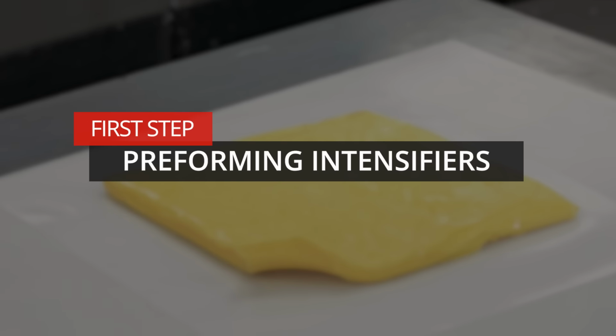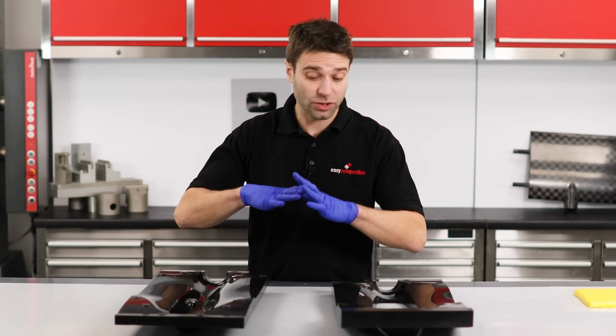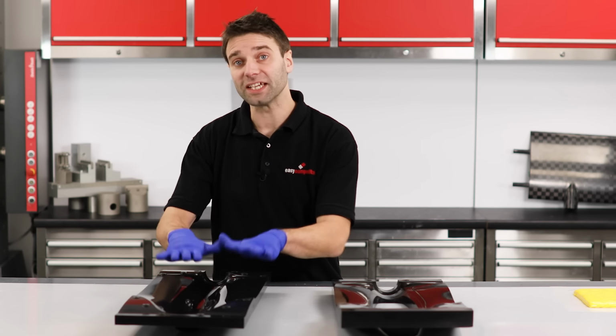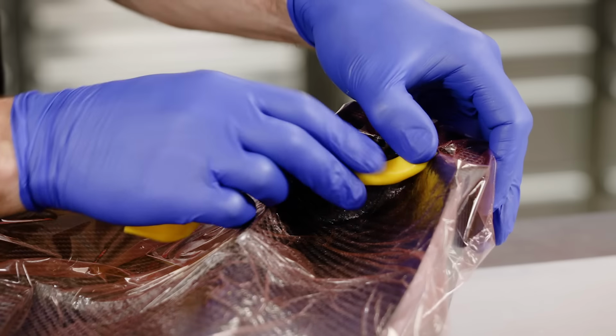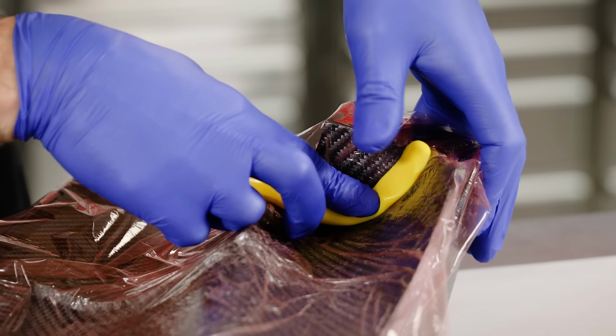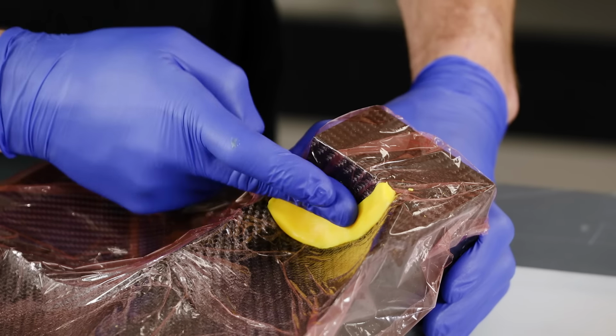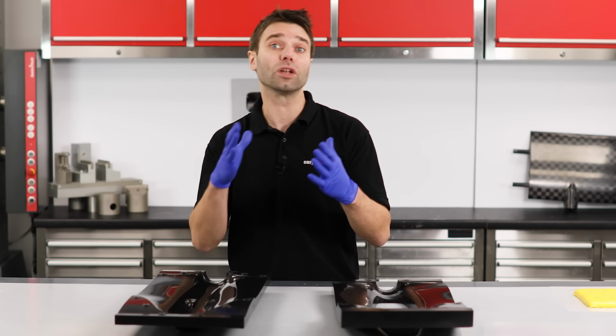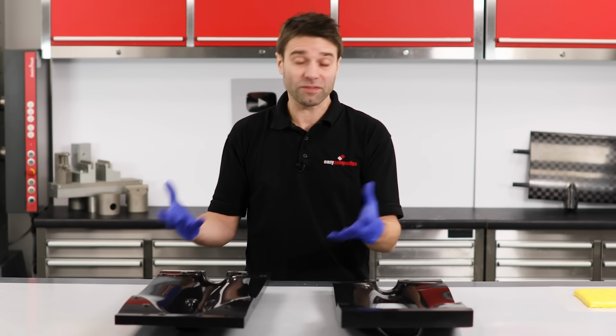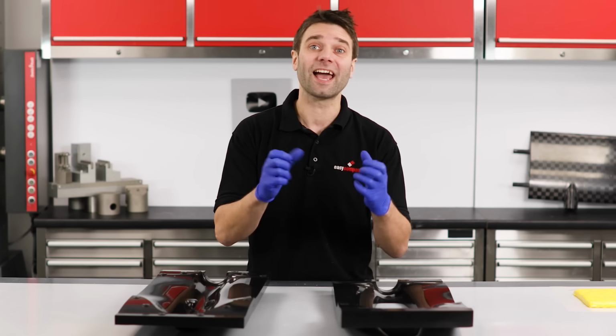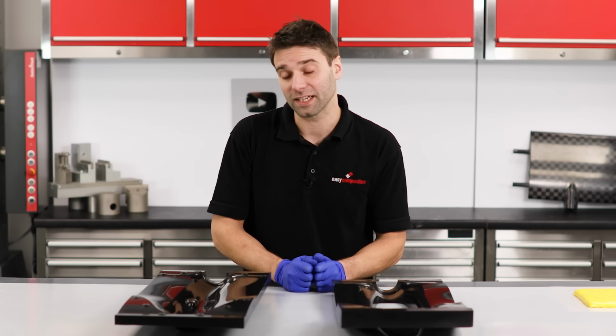The most common way to make your silicone intensifiers is to do your layup as normal, put your release film down, and then press the intensifier material into any of the complicated areas. This is then cured under a vacuum bag in the normal way, and your silicone will cure alongside the prepreg, and after demoulding, you'll be left with your part and your reusable silicone inserts.